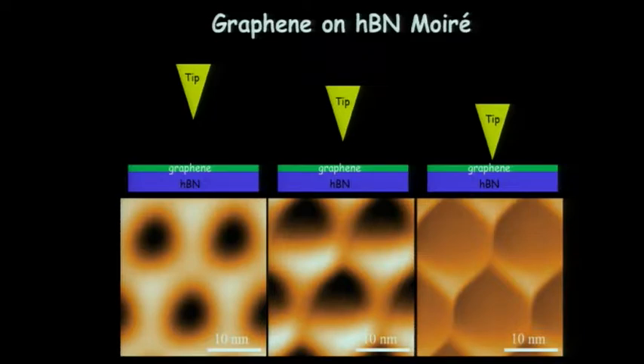So we're changing the bias current, we're changing the imaging conditions here, and we're working in this case with our tip very far away, so it's essentially very low current. And as you increase the current, you bring the tip closer and closer to the surface. This is the same exact area of the graphene substrate, and all we're doing is changing the imaging conditions. You can see that the Moiré pattern changes quite dramatically just as a function of this tip sample separation. So we go from a smooth Moiré here to these very sharp lines here.